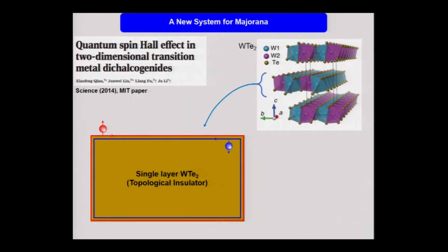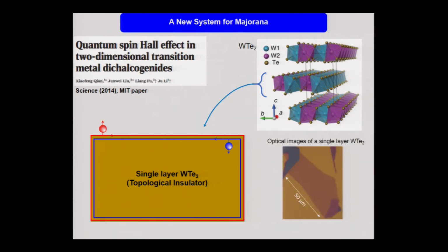So if we can achieve the single layer, then you will have an insulating bulk and conducting edge, where spin up and spin down travel in different directions. So I wanted to see in experiment whether this prediction is true or not. And this is the optical image of a single layer that we fabricated in the lab. Even though it's only a single three-atom thick layer, we can still see it clearly in optical images. Now we want to demonstrate whether it's a topological insulator or not. To do that, there are some relatively standard checks. But I would like to give the answer first, which is yes.